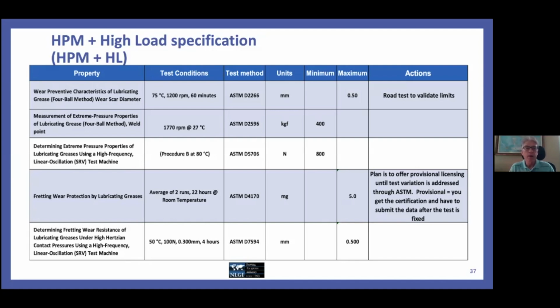So the 4-ball wear test, standard conditions, but we have lowered the maximum limit from 0.6 in the HPM Core Spec to 0.5. There was a lot of discussion here that it may be challenging to meet the 0.5 with an EP grease that carries the 400 kilogram weld load that we show in the next line. So the road testing will be to evaluate that and make sure that the 0.5 is not too low for this high load carrying category. But we agreed widely with the 400 kilogram minimum weld load, and this compares to the 250 kilogram weld load in the HPM Core Spec.